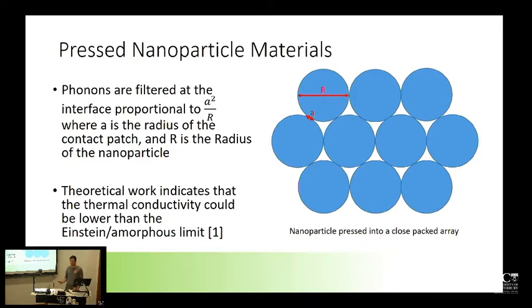The idea is that in the amorphous limit of the material, things are being scattered as much as they possibly could. They are as randomly scattered as they possibly could be, so it's almost at the limit of thermal resistivity. But there are various materials which exceed this limit or go beneath this limit by imposing more order on the structure, and these pressed nanoparticle beds are one of those structures.